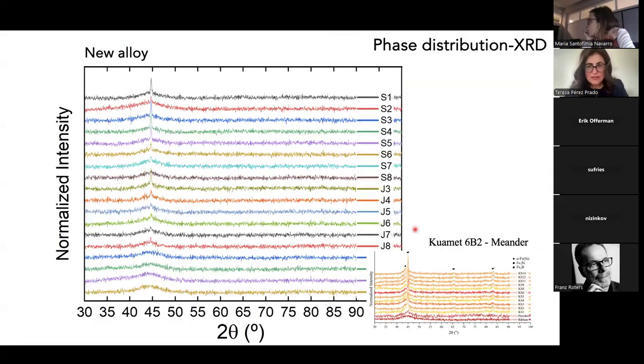And then, of course, phase distribution, which is the big challenge that we have here. Again, this is a large number of samples of these new alloys manufactured within the high power region. We don't need to distinguish between them because they all look very similar. And the bottom pattern here corresponds to the melt-spun ribbon of the same alloy.